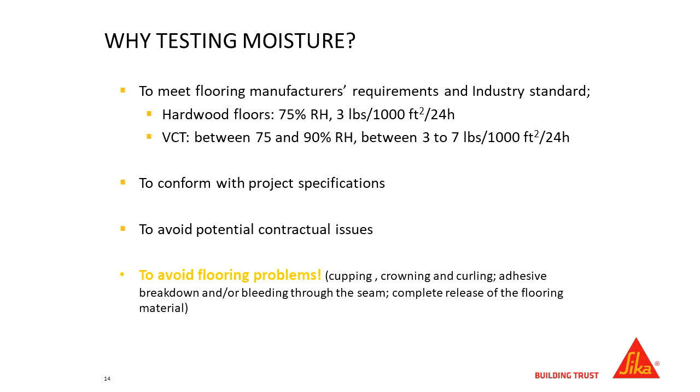With moisture, you get cupping, you get crowning, you get curling of seams. The key thing is you get adhesive breakdown. The adhesive will re-emulsify and no longer hold the flooring in place. You'll get bleed through with the seams. You see a lot of that with VCT adhesive, bleeding through at the seams. And your worst case, you have a complete release of the flooring material from the floor, which I've seen a number of times.